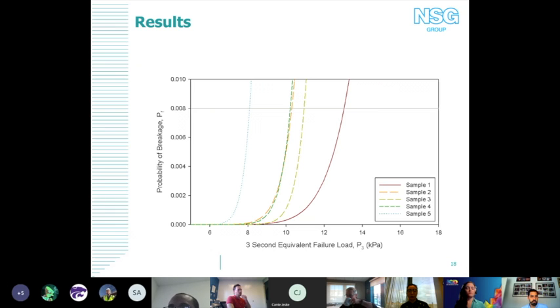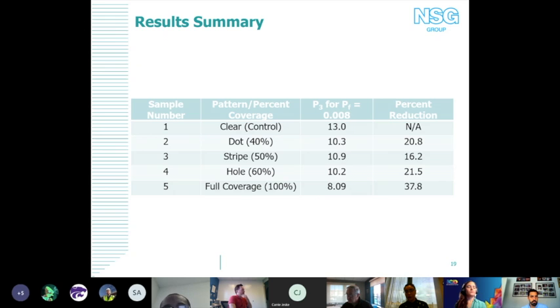And here's just at a probability of failure of 8 in 1,000. So you can see what that looks like with regard to E1300 design. What we saw was a load resistance reduction ranging anywhere from 16 to 38%. Interesting to note that samples 2 and 4 are fairly close in their percent reduction, and their patterns were exactly the inverse of each other, right? So it may have something to do with the layout of the pattern versus the stripes, which followed a different layout. I don't really have an answer for that necessarily, but essentially what we're seeing is that you're still getting fairly significant reduction.